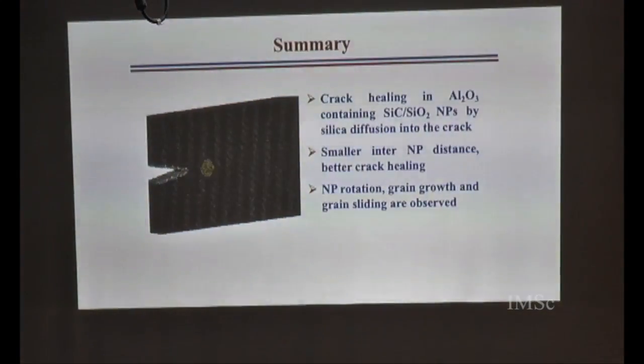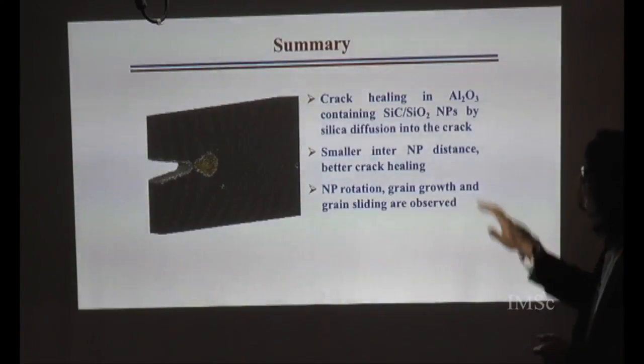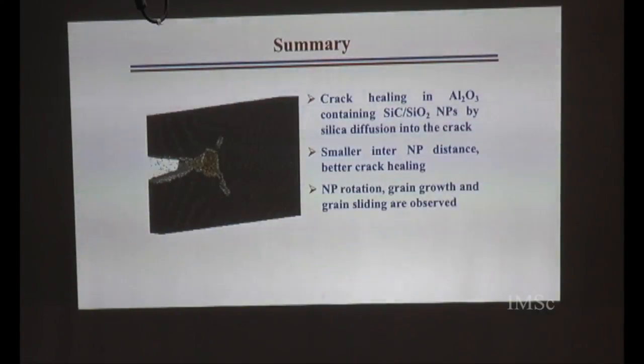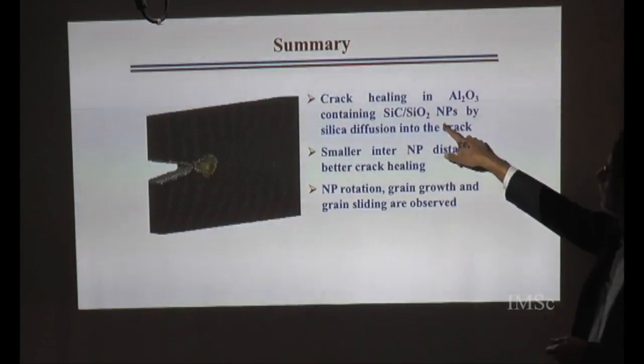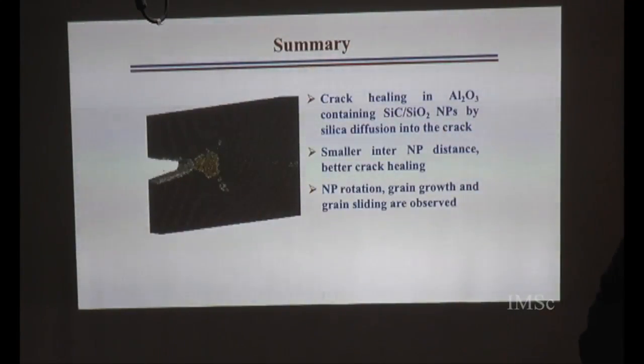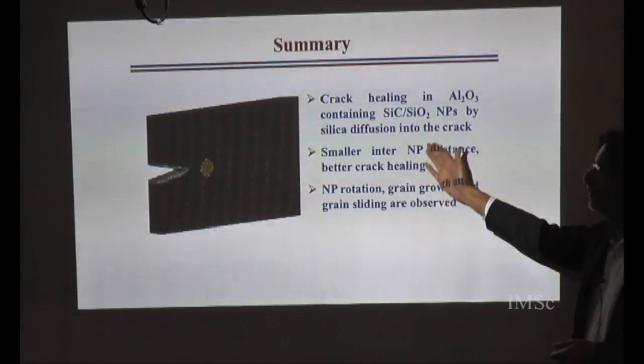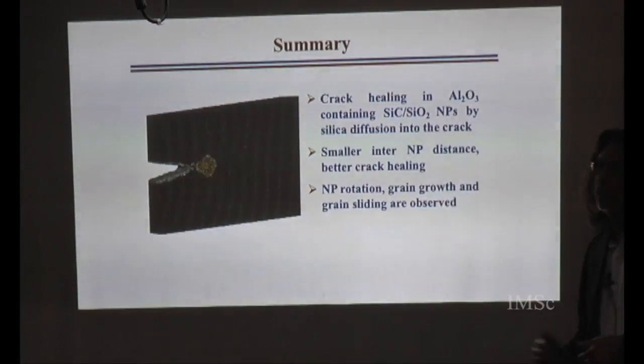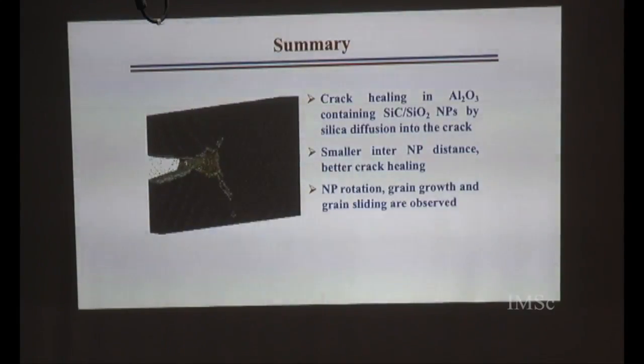And so the summary of this is that crack healing does indeed occur in alumina when you embed it with silicon carbide particles as the core and silica as the shell. And silica is really mainly responsible for healing the cracks. And in addition to the healing, what you see is nanoparticle rotation, grain growth, and grain sliding in the system. So these are the three simulations I wanted to describe to you.